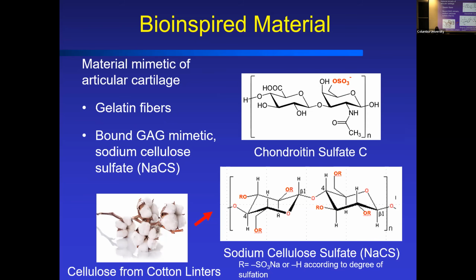So shown here, out of cellulose, just cotton linters, we are able to sulfate that cellulose such that we can actually vary the degree of sulfation. And so that's a big finding. If you look at the structure here, those R groups, we can substitute in those sulfate groups, and we can achieve a relatively high degree of sulfation. And what we found in some work is that that helps to promote the sequestering of growth factors. And that's key, again, for presentation to the cells, and that promotes chondrogenesis. So I'll show some of that work. Varying that degree of sulfation improves biological performance of the materials.